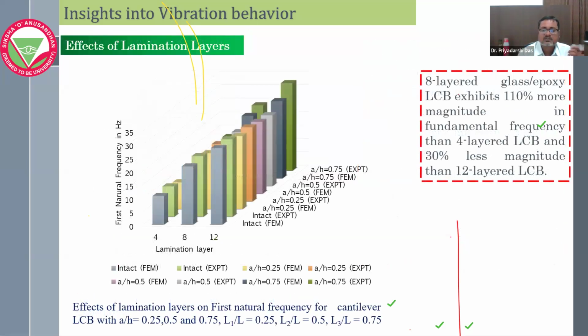Then the lamination layers. There is a 4-layer, 8-layer and 12-layer lamination. As you can see, from 4-layer to 8-layer, there is a significant jump. But from 8-layer to 12-layer, the jump is quite insignificant. And in that line, if we calculate from 12-layer to 16-layer, and 16-layer to 24-layer, again that jump will diminish. So a time will come where there will be no increase or decrease in the frequency.